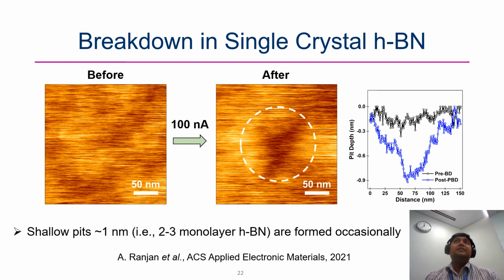Other than CVD hBN, we also wanted to understand if this breakdown is an intrinsic property of the material itself. So we used a single crystal hBN, which was grown by the high pressure, high temperature thermal gradient method. What we are seeing here is the topography image before and after we applied electrical stress using ramp voltage stress, keeping the current compliance at 100 nanoamps. What we saw is that after electrical stress, a pit is formed, and the size of the pit is around 3 monolayers. So the pitting seems to be common to both materials, grown by CVD as well as the high pressure, high temperature thermal gradient method.